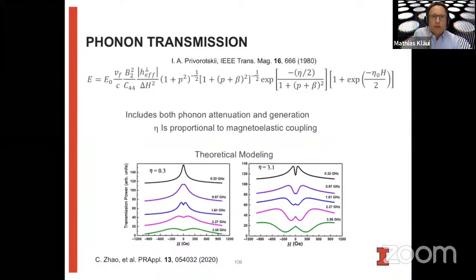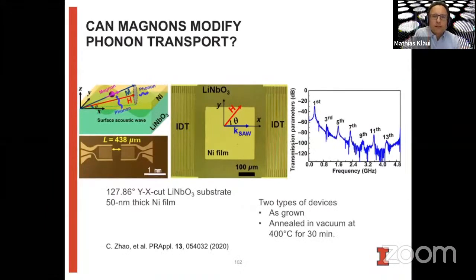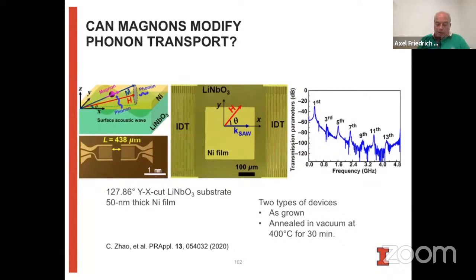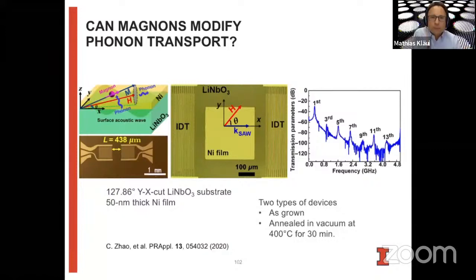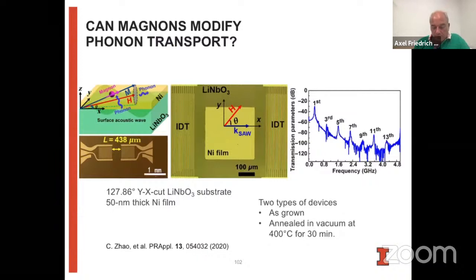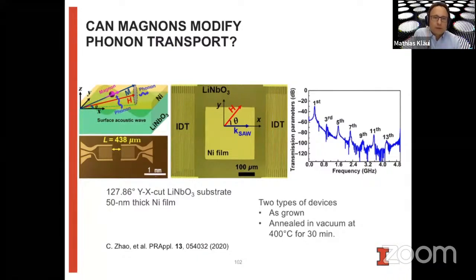So how far do actually phonons propagate if you launch them somewhere? What is the decay length as a function of the frequency? Oh, look, the device here is like half a millimeter, right? Mm-hmm. So you can easily have millimeters, centimeters, no problem. And do you know how the quality of the substrate influences then the enhanced line width of the magnons? Because you need energy dissipation in the phonon bath to enhance the magnon line width by this magnetoelastic coupling. I'm asking because there's this work by Eiji Saitoh where he looked at these magnon-phonon polarons, and sometimes the acoustic quality of the material was better than the magnetic quality, and sometimes the magnetic quality was better than the acoustic. In your case, you always increase the line width of the ferromagnet by coupling to the phonons.